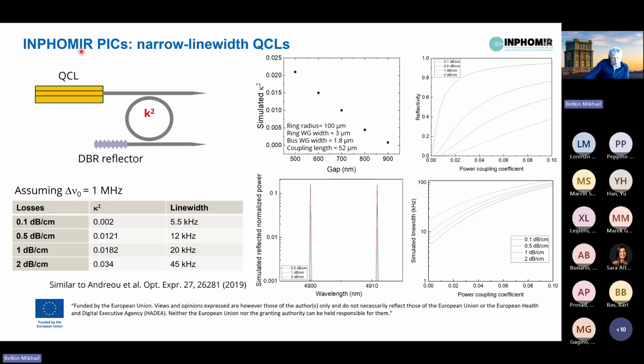And then we are also working on the first mid-infrared photonic integrated circuits to produce narrow linewidth lasers. The concept is similar to what Javier has described already for near-infrared. The idea is to couple an active device to a passive section with a long effective passive length. This configuration is known to reduce the linewidth of the active device by simply increasing the length of the cavity, so that the fluctuations due to spontaneous emission and carrier fluctuations in the laser and alpha factor of the laser are suppressed because the actual laser cavity is much larger than that of just the laser.